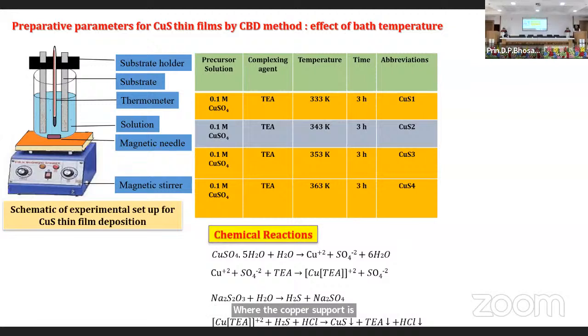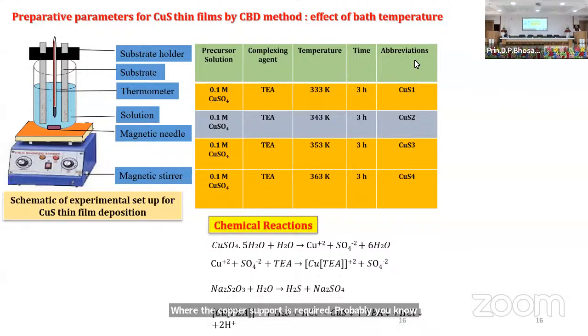Probably you know that the earlier solar cells were based on the cadmium sulfide, copper sulfide. Cadmium sulfide is N-type, copper sulfide is P-type material. So you can make the cadmium sulfide using the same method. You can also make the copper sulfide using the same method. If you could make the layer one over other, you can form the junction also. A PN junction can be made using simple method if you deposit the other one material over other material.